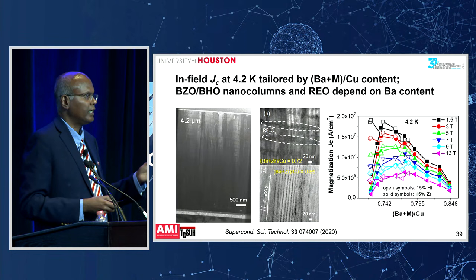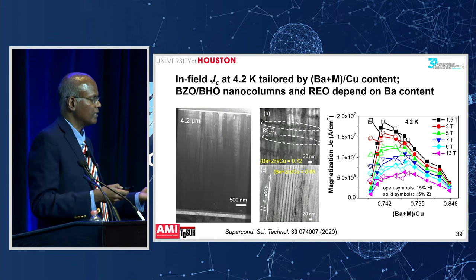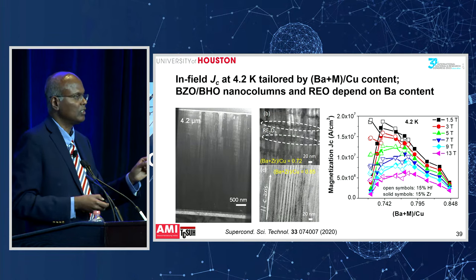So it's a combination of tailoring the epitaxy by this advanced MOCVD process, but also being able to control the composition and get to a stage where you can actually refine the size of the barium zirconium nanocolumns and get much higher performance than was feasible.